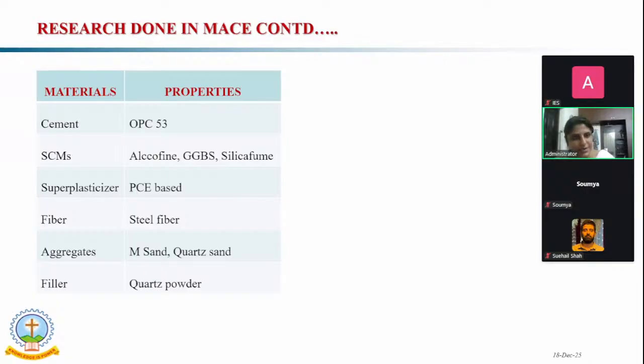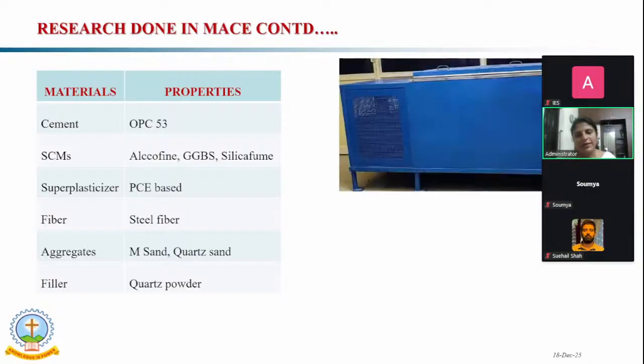We have considered steel fibers with aspect ratio 100. Then we have considered M sand, coarse sand, river sand, standard sand, all. In the case of filler, we have checked quartz powder and limestone powder, but finally we agreed with the quartz powder.